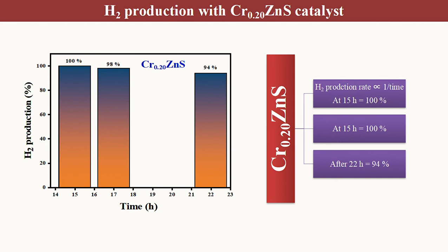The hydrogen evolution decreased from 100% to 94% over the chromium zinc sulfide after 22 hours of the reaction time. A decrease in hydrogen production over time might be due to the deactivation of the photocatalyst.